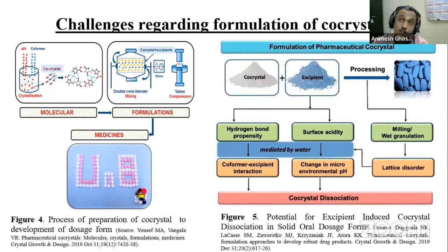So that is why that co-crystal excipient compatibility study is very much important for the formulation. Then another thing is surface acidity, because say the excipient is basic in nature or acidic in nature. In that case also, the surface pH or microenvironmental pH will play a role during the granulation technique, and ultimately if we don't get the co-crystal in its intact form in the tablet, there will not be any profit out of this. So during milling also there might be a chance to break the hydrogen bonds, right?